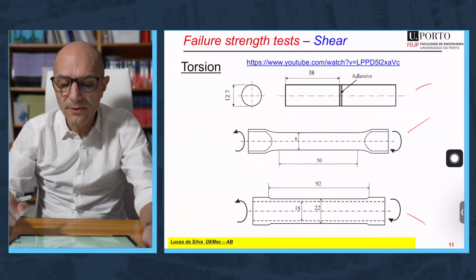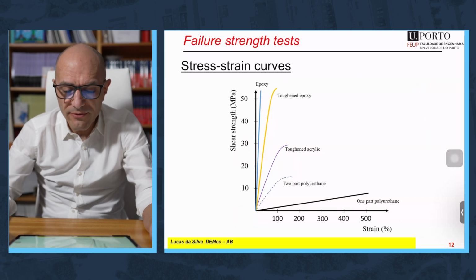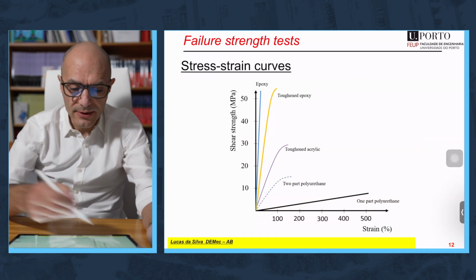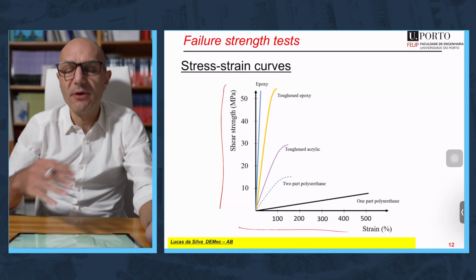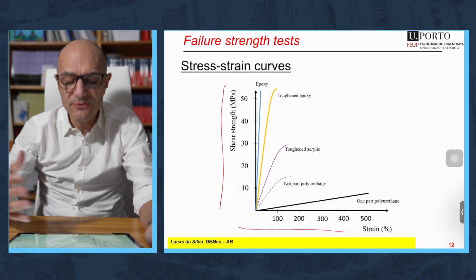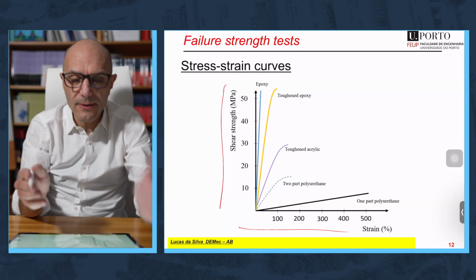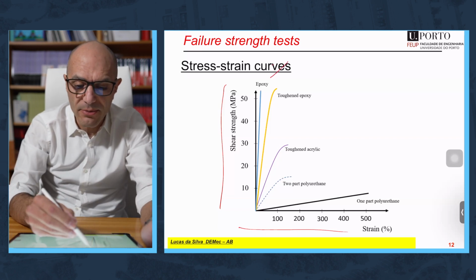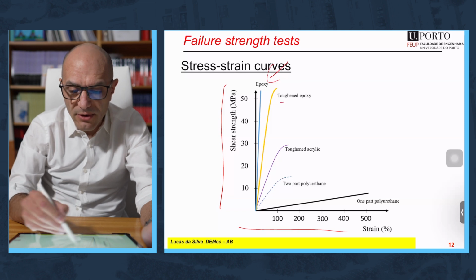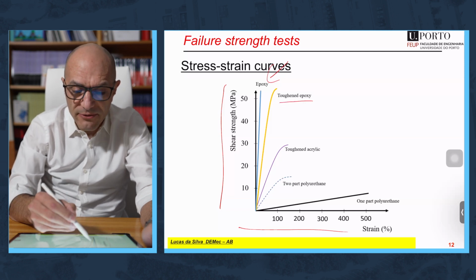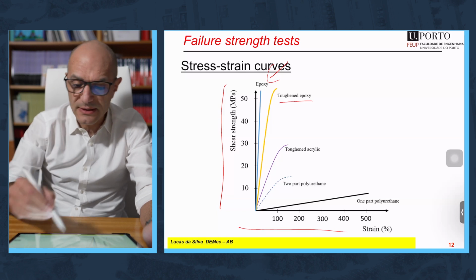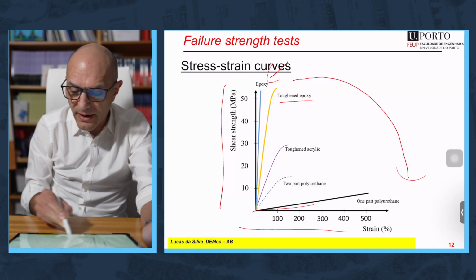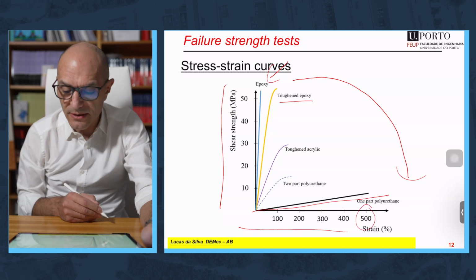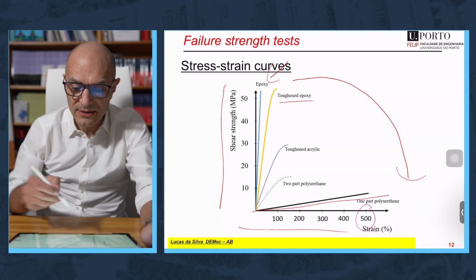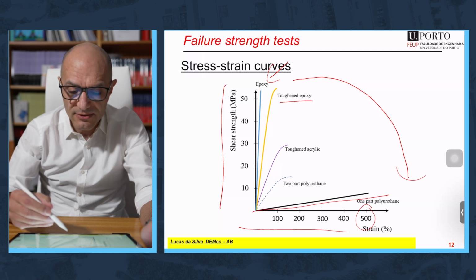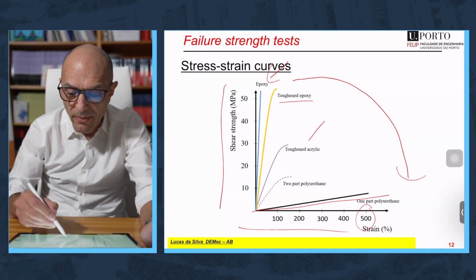So that's for the video. And finally, you have here a plot in a shear stress-strain diagram of the main structural adhesives used. In one part of the scale you have the strong epoxy adhesives, then you have the toughened epoxies. They are not as stiff as the pure epoxy, but they have an increased toughness. And in the other part of the scale you have the one-part polyurethane that can go up to 500% deformation, the windscreen for example. And then in between you have all the other structural adhesives we discussed, the acrylics and the two-part polyurethane.